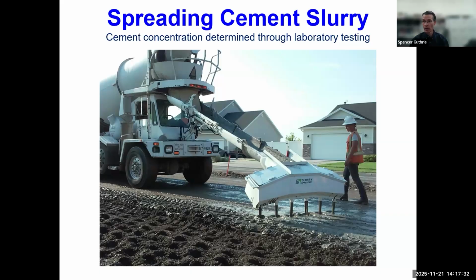Indeed, I'll mention, Samaya will especially appreciate this. Salt Lake City has some pavements, concrete pavements, that are now more than 100 years old. So it's phenomenal. When the roads are built right, as long as we've taken care of those underlying utilities, we may not have to touch the road again for a long time. So based on the laboratory testing, we might recommend 2 to 4 to 6%. That's common. The most cement that we can reasonably apply and mix in on a job site using this process would be about 12. And that would require 2 passes, each at 6%. After that, it's just too much cement. We should consider some other options like over excavating the site, replacing the material with better material, etc., just from an economics point of view.